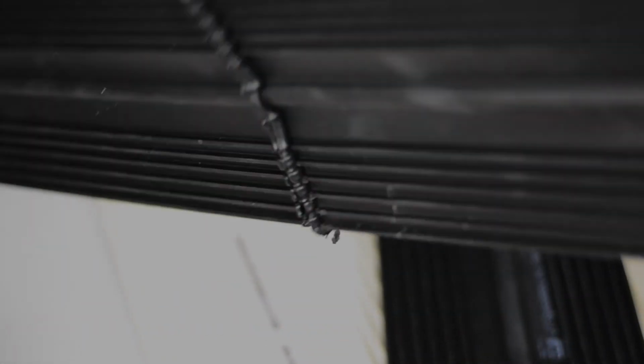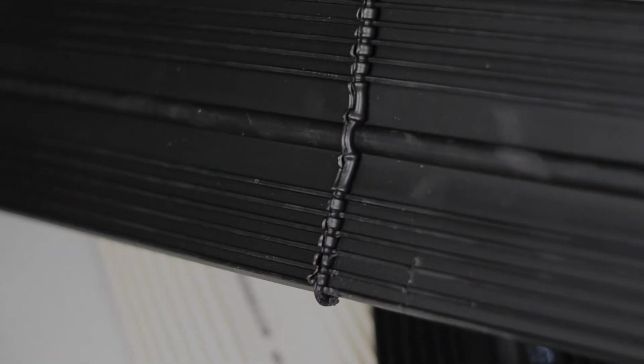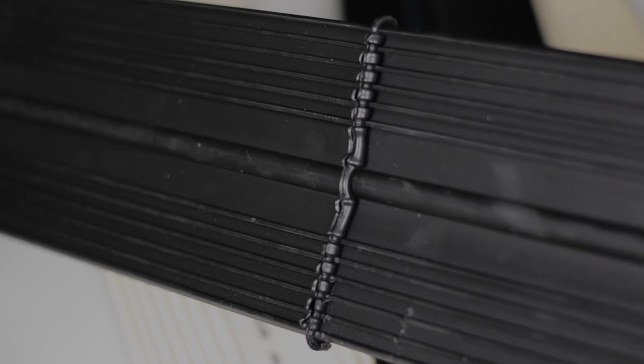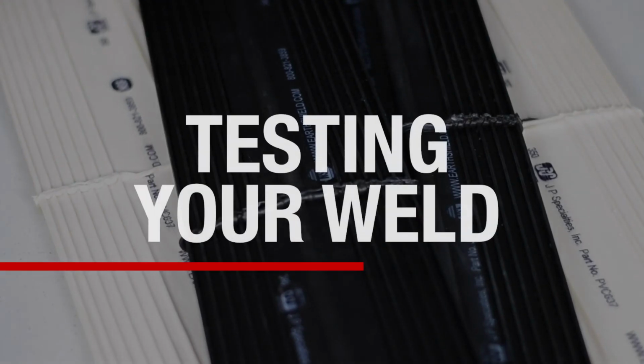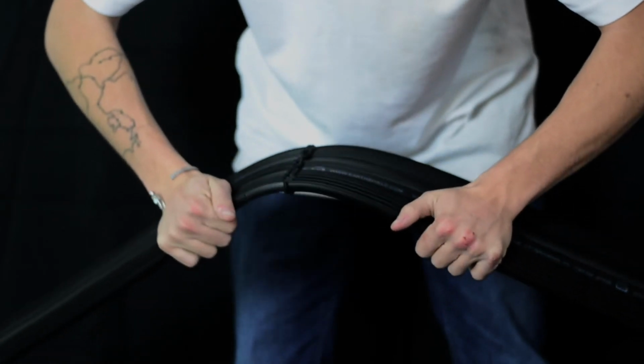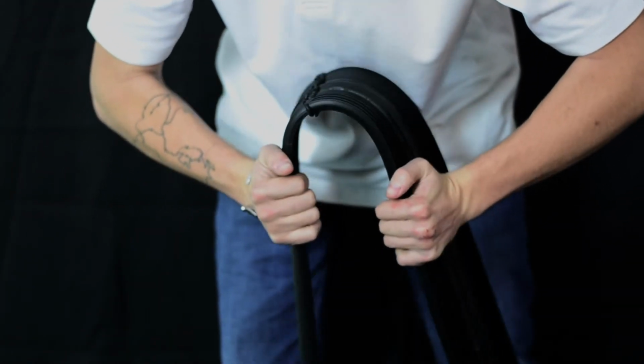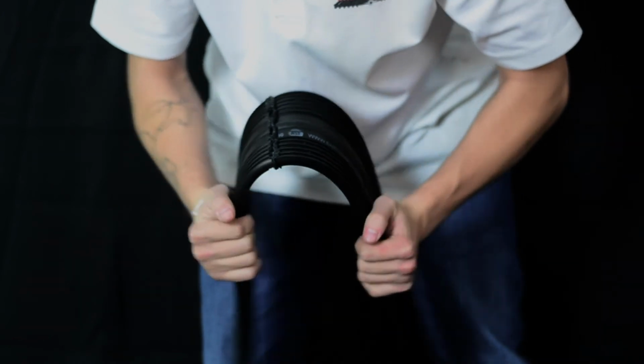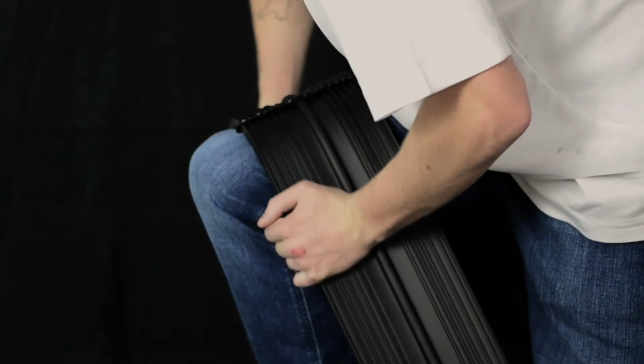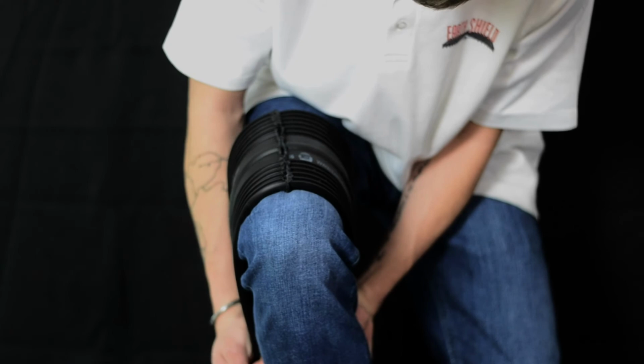When cured, a proper water stop weld should be homogeneous and retain 80% of the parent material's physical properties. The best way to check weld quality is through several destructive tests. The weld should not be able to break through moderate amounts of shear force. If you can break it over your knee, you need to try again.